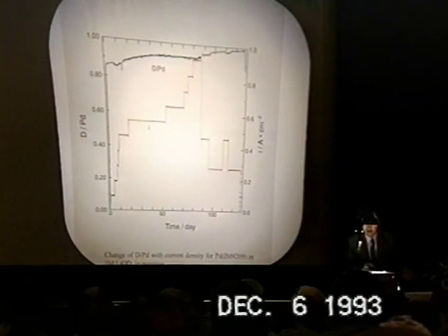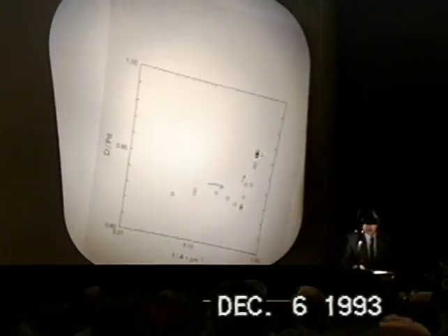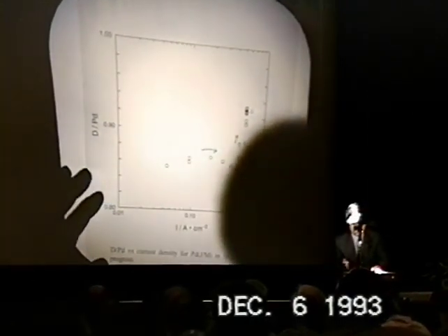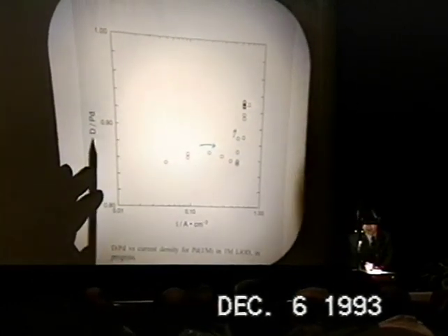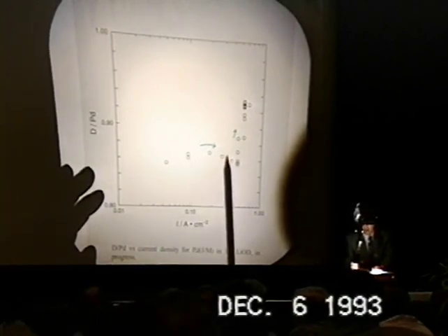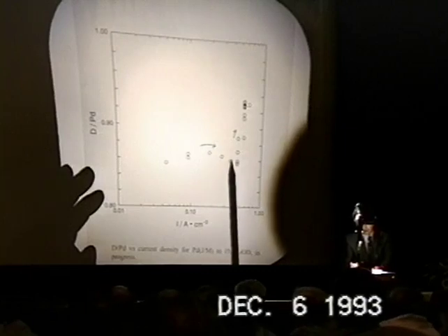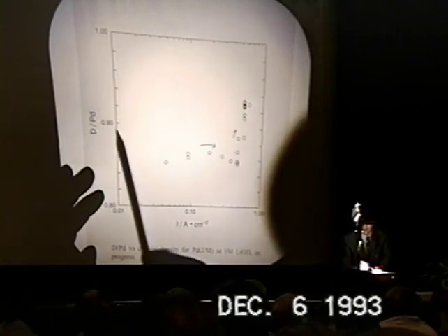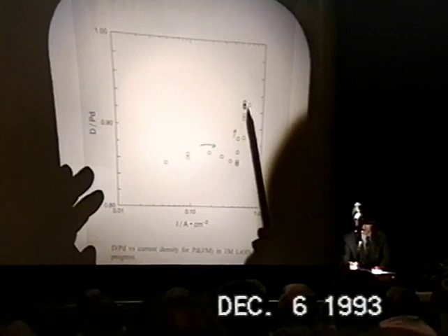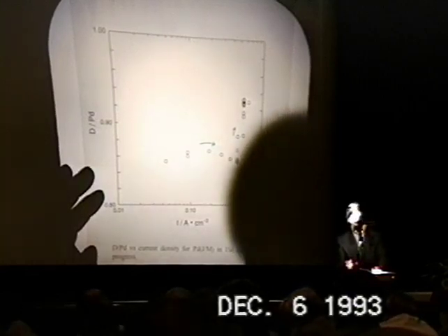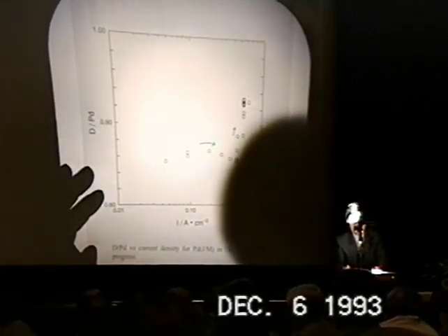We have a similar tendency with the Johnson-Matthey palladium electrode, which is shown here. So the loading ratio versus current density goes to something like a small minimum, and then went up again to a value higher than 0.9. In this case, we are seeing a loading ratio of 0.94 at nearly 700 milliamperes per square centimeter.